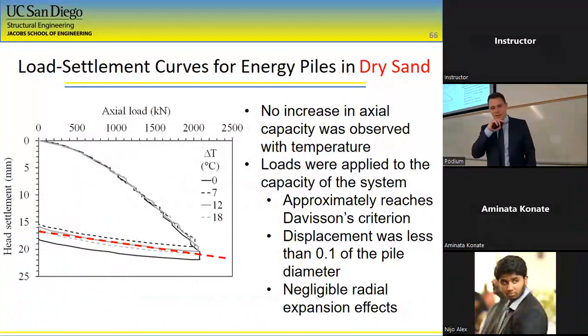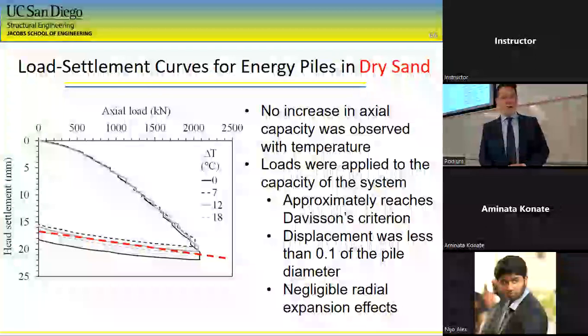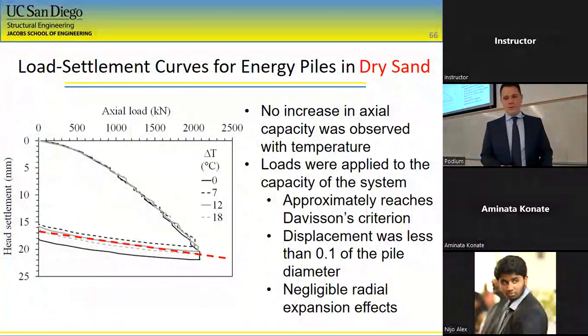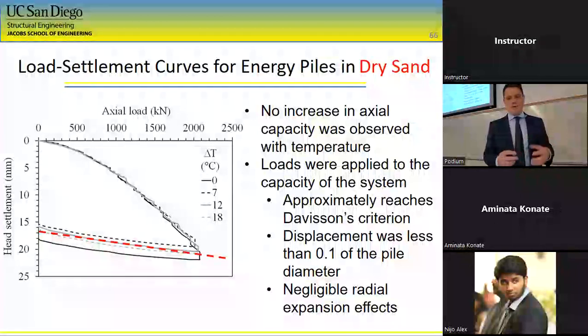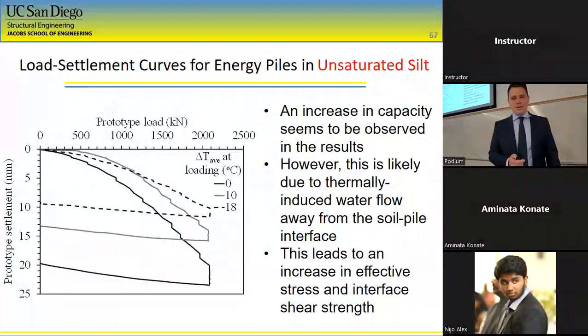So first we did tests on dry sand, and you can see we did 4 tests there under different temperatures, and the shapes of the load displacement curves are almost exactly the same. So there's no change in capacity of the pile with temperature. We even kind of expected that potentially there was an increase in radial stresses, and then that could lead to some increase in capacity, but that was a very small effect.